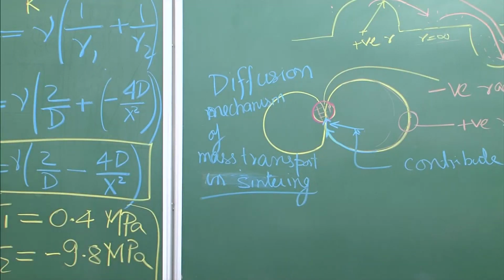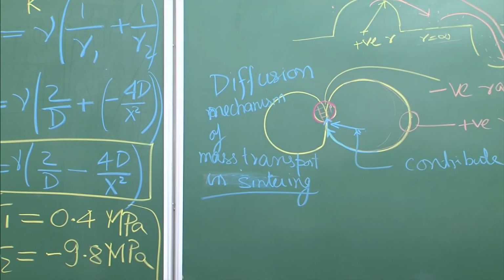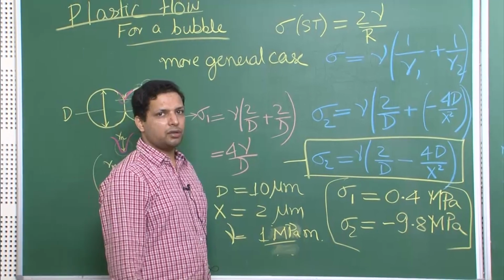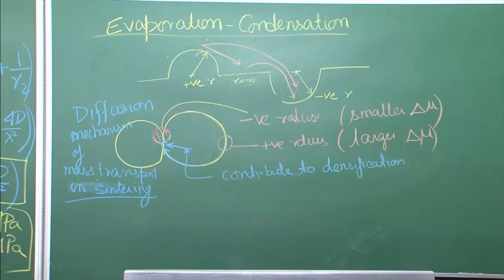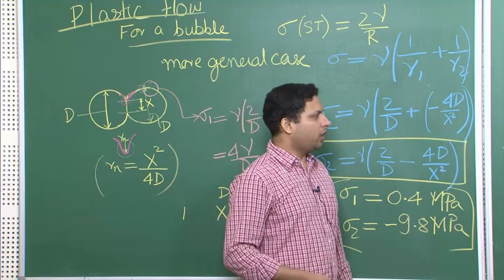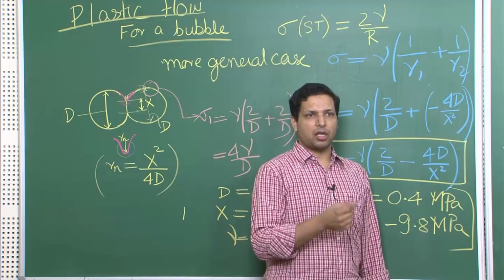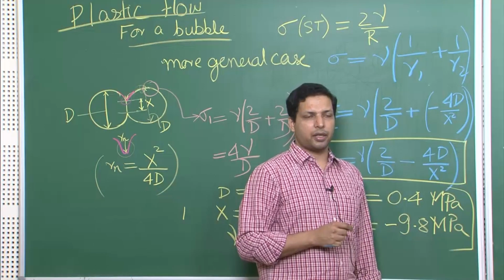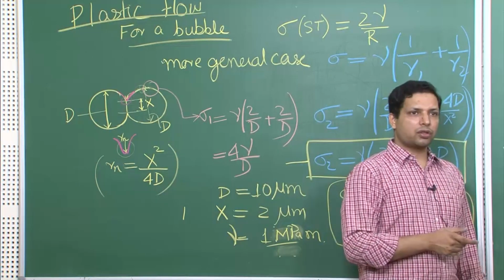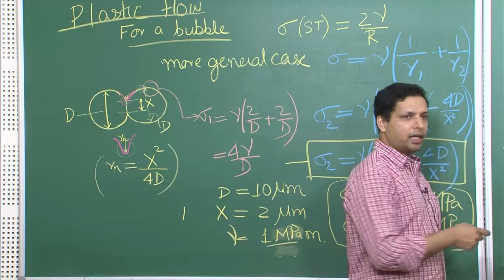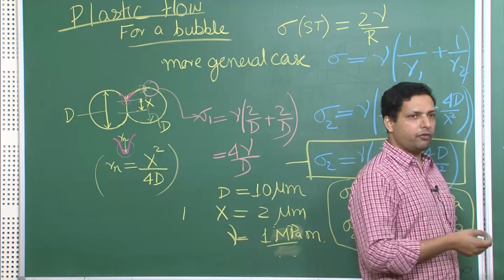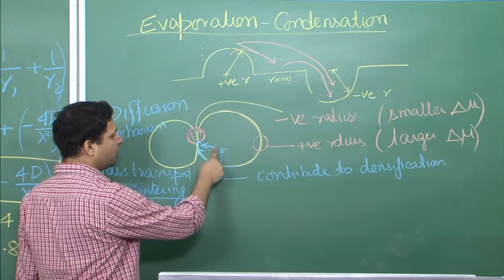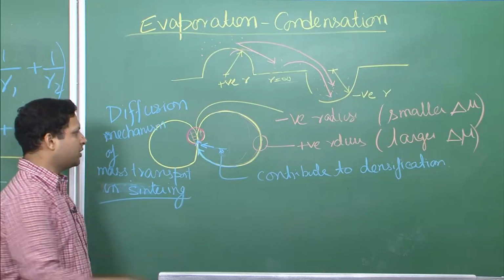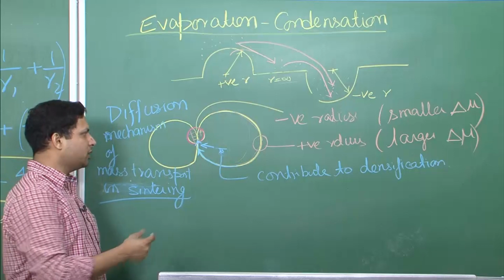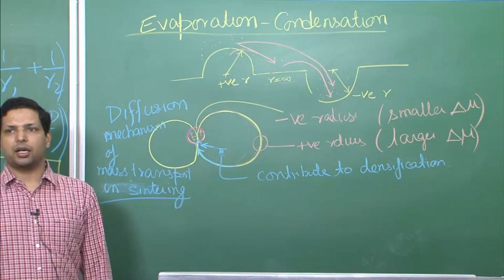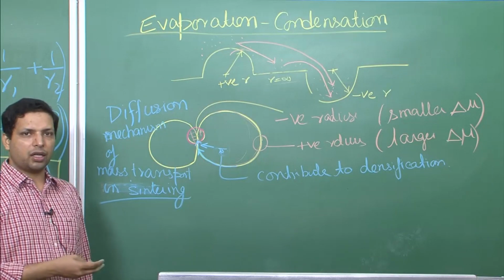So, we have seen three different mechanisms. One is the plastic flow, second is the evaporation condensation, and third is the diffusion mechanism of transport in sintering. And we see that all of them will contribute to coalescence of the particles by mass transport of material from other regions into the neck region. However, densification is limited to only certain particular cases, and that will depend from configuration to configuration. In one particular case we know that, for example, when diffusion is taking place from inside the powder particles to the neck, in that particular case we will get lattice diffusion, and we will get densification.